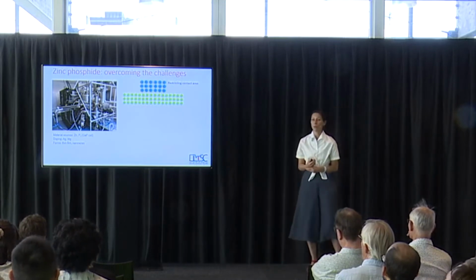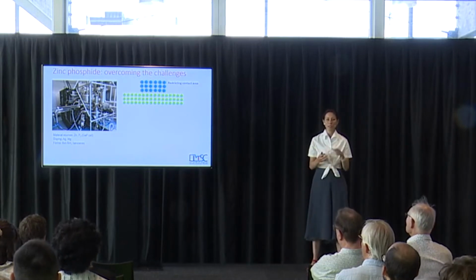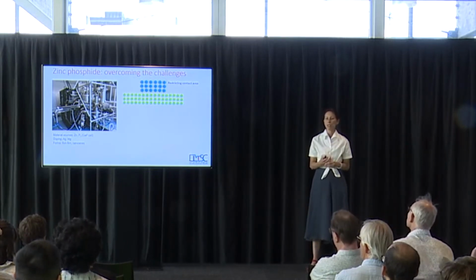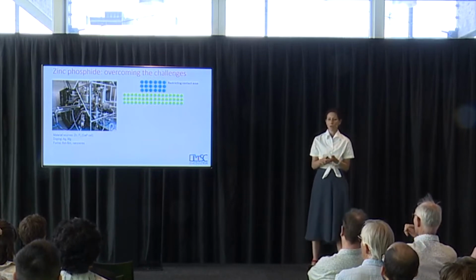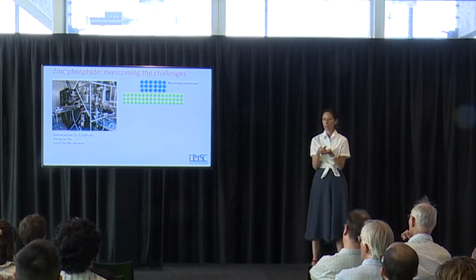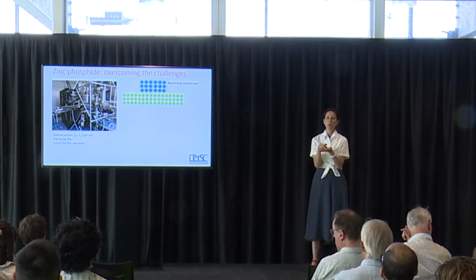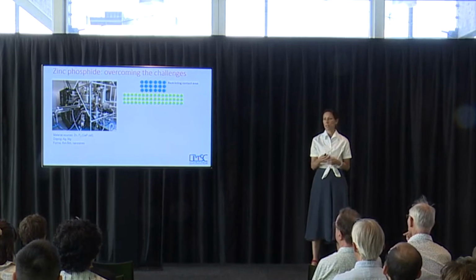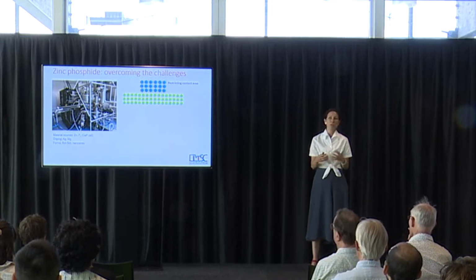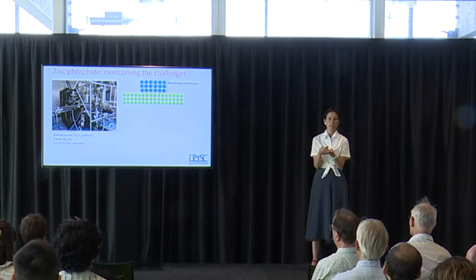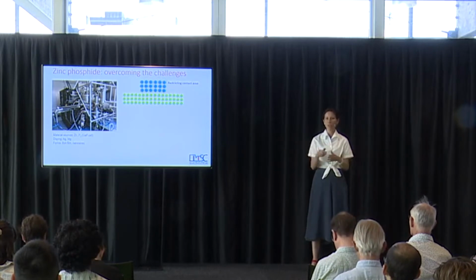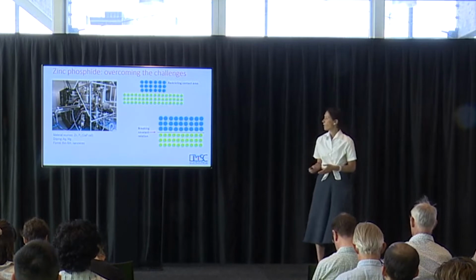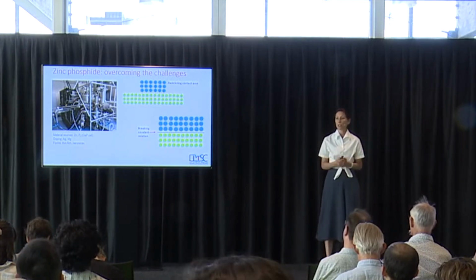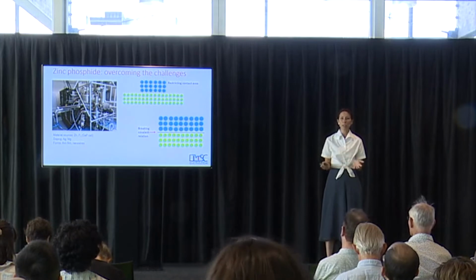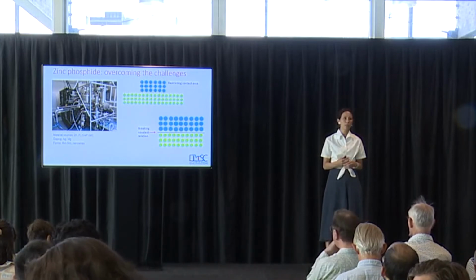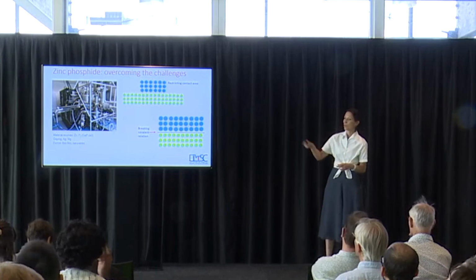So the way to go around the requirement of having a crystalline substrate that matches the structure of your material can be done differently. One way is you can start growing your material in nanoscale form, like we did with nanowires. If the footprint with the substrate is very small, then all these issues with the lattice mismatch and mismatch in the thermal coefficient of expansion, you can go around this because the stress that you create there is much less than when you have a large interface. This is one way. The other way is that you can just try to break this relation with the substrate by having a substrate that will not have any covalent bond. And this is typically 2D materials like graphene. So I will show you results on these two ways.